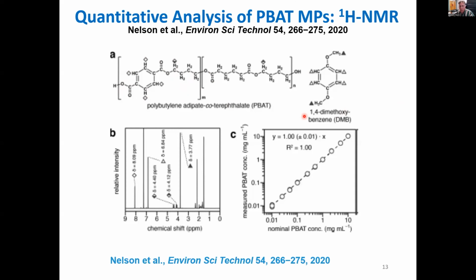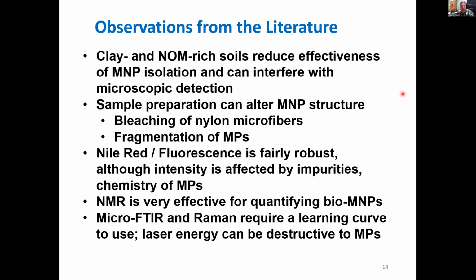Often we have to use a second internal standard to get really good quantification. These are just some observations from the literature that I have seen. One of the issues is the soil type. If we have soils that are rich in clay or natural organic matter, that really affects our ability to recover microplastics from the soil. And also they can produce interfering compounds, especially for microscopic detection. In sample preparation there are a lot of potential pitfalls in using different techniques.